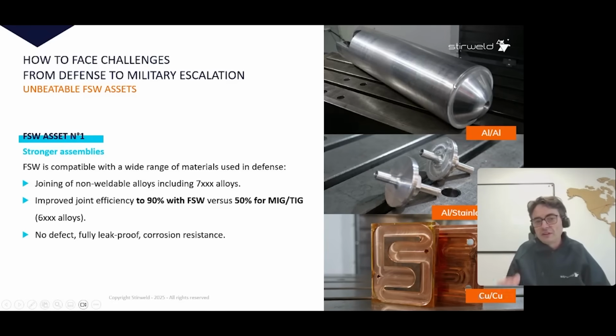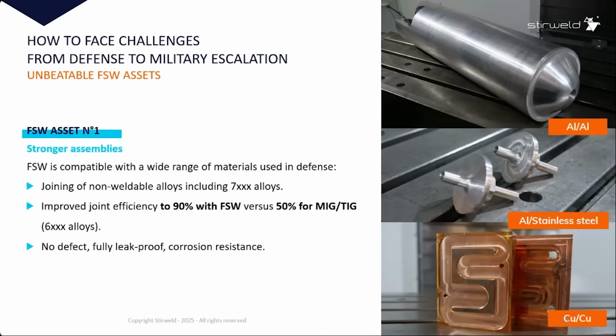As you will see on the next slide, we can weld any kind of aluminum alloy. Also, we can mix any kind of aluminum alloys. For example, you can weld a 2000 series with a 7000 series, and that is totally forbidden using liquid state welding processes. The second important point is that we greatly improve the joint efficiency. Generally using MIG TIG, we get a joint efficiency of about 50%, while with friction stir welding we can reach 90% joint efficiency. And you will also see no defect, no leak, no corrosion problem.